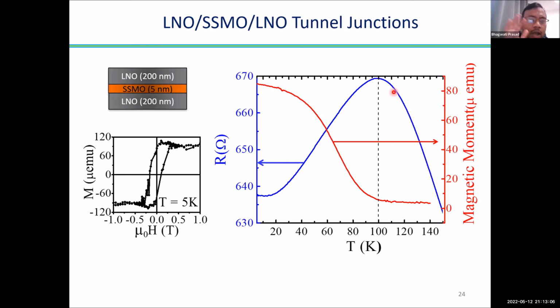Now, okay, let me come to the basic manganite systems. If you see the metal to insulator transition in the manganites, what happens? The metal to insulator transition at TC should be sharp, but it doesn't go sharp. It also goes gradually all the way down, so you see it broader. In fact, it depends upon the film thickness, how the strain is playing. There are various orders, like charge, spin, and orbital ordering taking place in this system. So eventually the magnetism in this system is not conventional, it is a different way, like either superexchange or double exchange mechanisms, and the oxygen orbitals play a big role here. And how much strain there is, what is the angle of the metal-oxygen-metal bond, that plays an important role. And how they may change with the thickness, and also when you make a smaller shape and size, all that matters a lot.